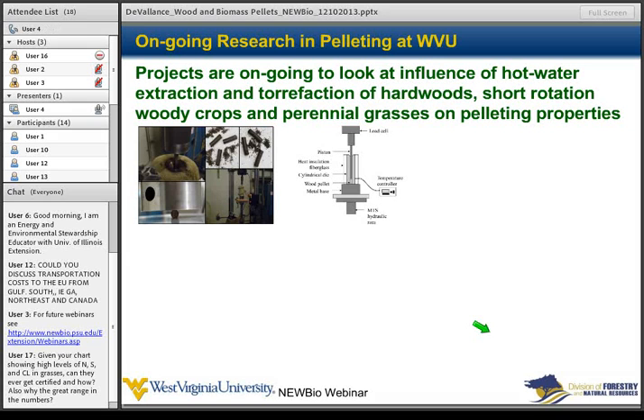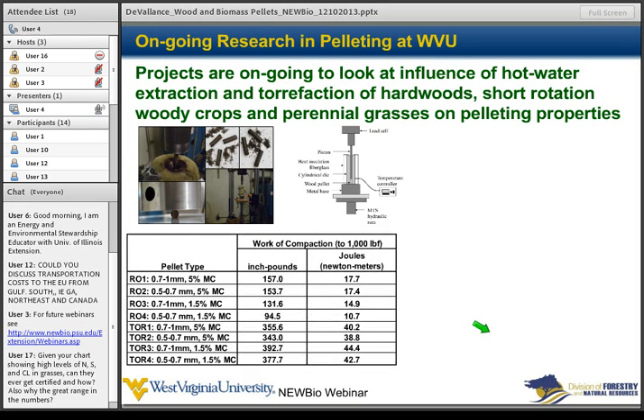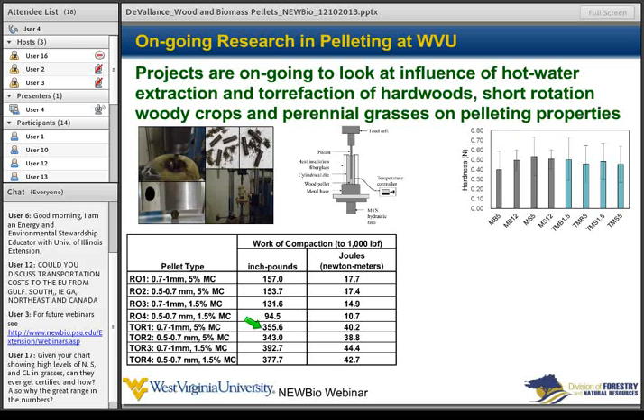We have a single pellet die that we use to study compaction behavior in these materials. We do a lot of work on compaction energy. This is red oak, not treated, and the compaction energy required to make a pellet. Then we torrefy that same red oak to the same treatment level of particle size and moisture content, and you can see the compaction energy goes up quite a bit. Those are some of the challenges with torrefied material: you increase the price just because of the energy required to make pellets.